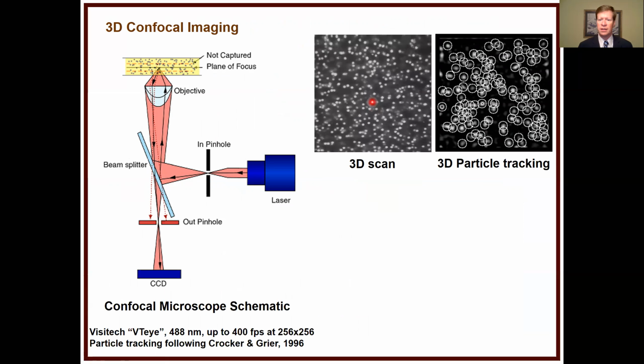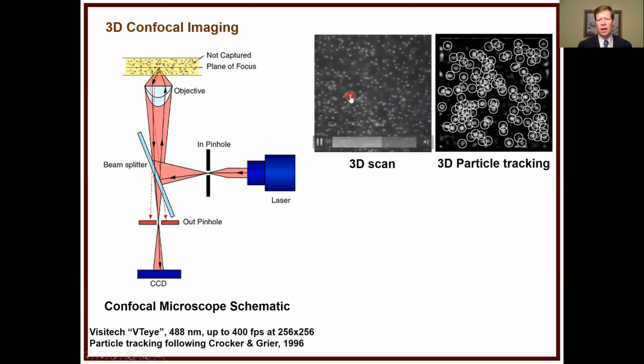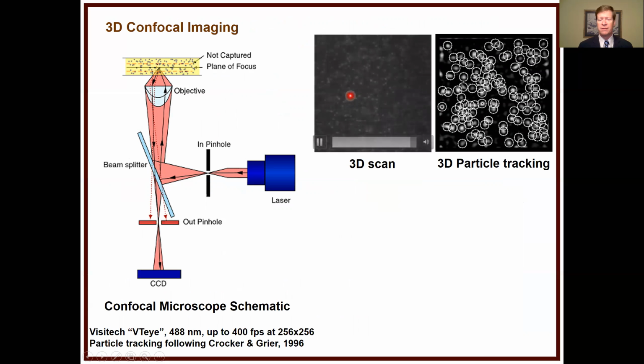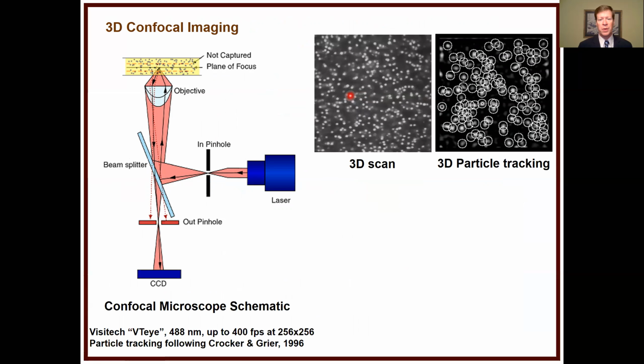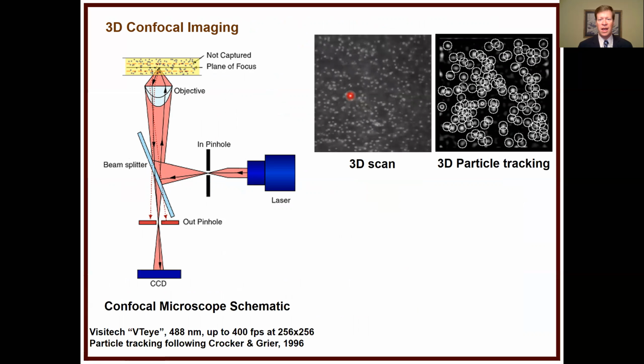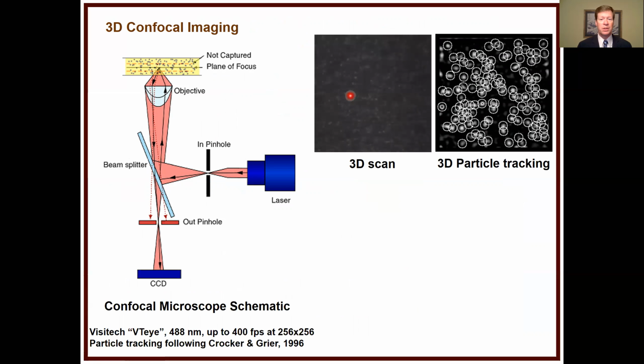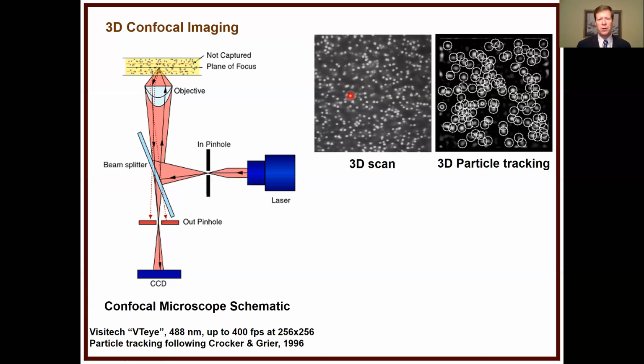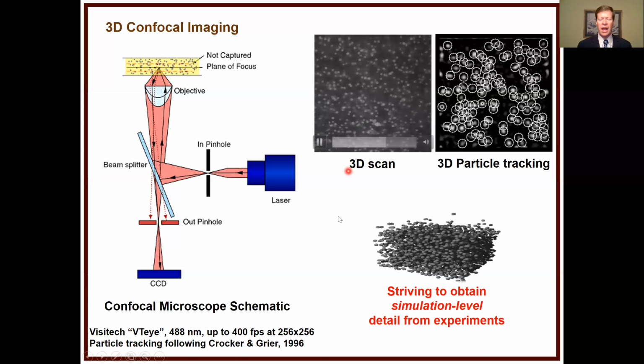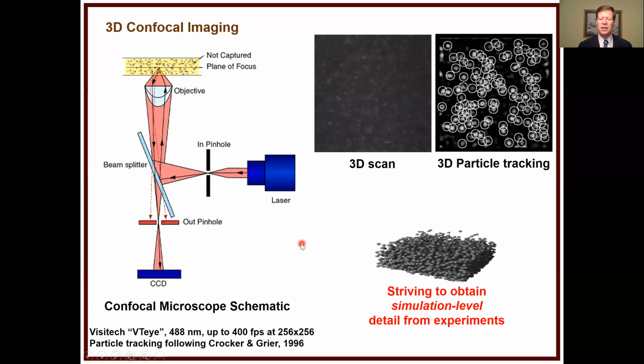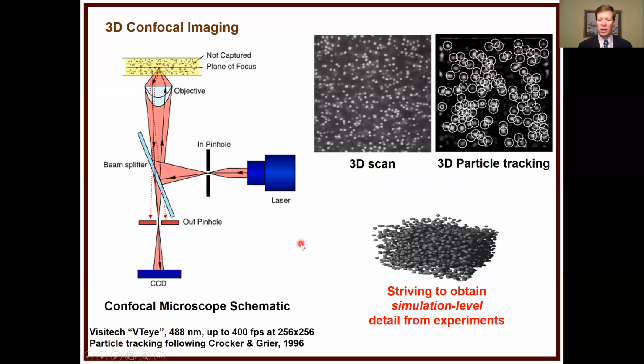We usually scan about a 25 by 17 micron volume, where each pixel is 100 nanometers. And we can do that every second. We typically do that every 30 seconds through an hour of drying. The goal here is to have simulation-level detail of these experiments, so you can really watch as things dry.